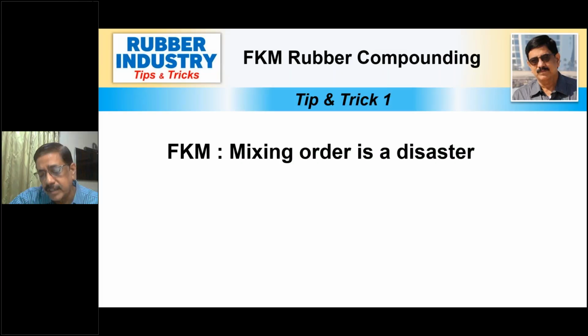Suppose you are using two different viscosities of rubber, you have to blend them. Then, once you blend it, come all the ingredients, the fillers and so on. As you all know, the cross-linking taking place in FKM is a chemical cross-linking, mostly inorganic cross-linking. Because of that, there is always generation of gas. Fluorine gas is evolved, hydrofluoric acid, HF, is evolved, and it is absorbed by magnesium oxide, and calcium hydroxide is activating this. So this is totally an inorganic reaction.